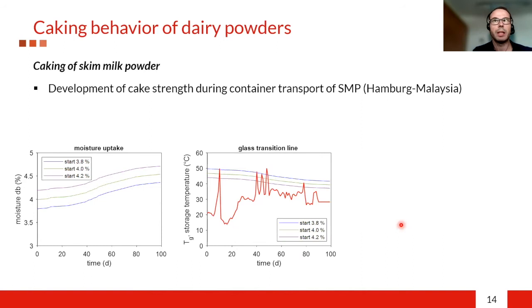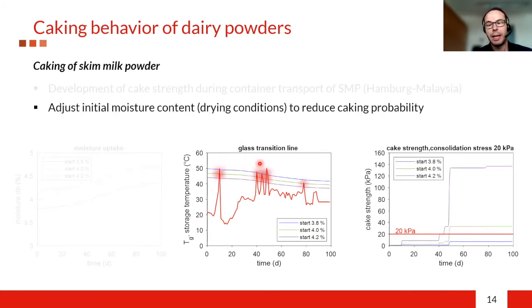Here you can see some results of this simulation, the development of the cake strength. At first, the moisture uptake in the bags. We simulated 3 different starting moisture contents from 3.8 to 4.2, and there is an increase in the moisture content because the water vapor permeates through the bag material. From this moisture uptake data, we could calculate the glass transition line, which is important for estimating the cake strength. We can see here that several times the storage temperature exceeds the glass transition lines. So 1, 2, 3, 4, 5 times the glass transition was exceeded, and that's why caking can develop.